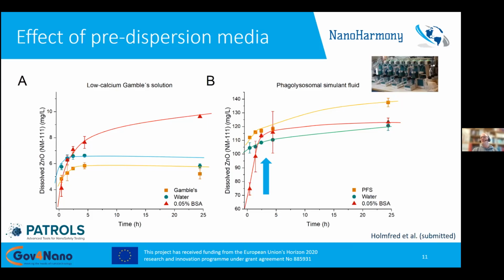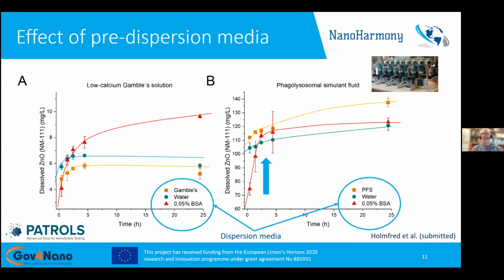So just an example on the effect of pre-dispersion. Here we looked into the use of different approaches, because different approaches have been discussed and proposed. So one is to disperse directly in the test media, so Gamble solution, or water alone, or BSA water, which is used in our standard method, the so-called NANOGENOTOX dispersion protocol, which bases dispersion on ethanol pre-wetting and a little bit of BSA in the water.